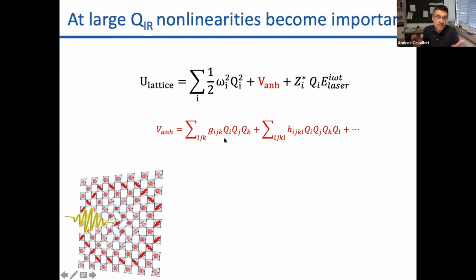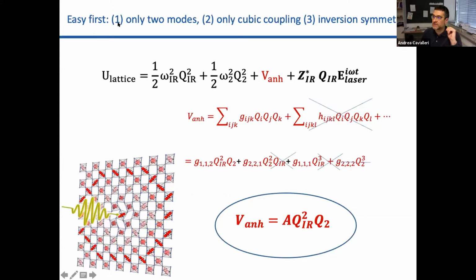And so, without knowing anything about the material, the anharmonic coupling term will include all the coupling between all different phonon modes, the third, fourth, and higher orders that will participate in determining the energy of this driven material. Okay, so for the purposes of what I'm going to tell you in the next few slides, we should simplify this problem as much as possible. So we're going to make three approximations. First, we're only going to consider two modes, so we're imagining a material that only has two modes, one that I'm driving and another one. I will restrict myself to the lowest order coupling, the one that only mixes three phonons cubically. And I will also imagine the material being inversion symmetric.